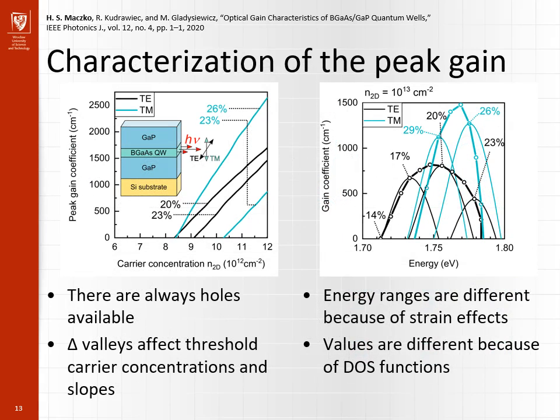In these quantum wells, holes are always available in the quantum well in much greater numbers than electrons. Delta valleys greatly affect the energy of the quasi-Fermi level in the conduction band, so they are the key factor determining threshold carrier concentrations and slopes of peak gain values as functions of carrier concentrations, shown in the left panel. Strain effects affect the direct gap similarly in both cases of strain, compressive and tensile.